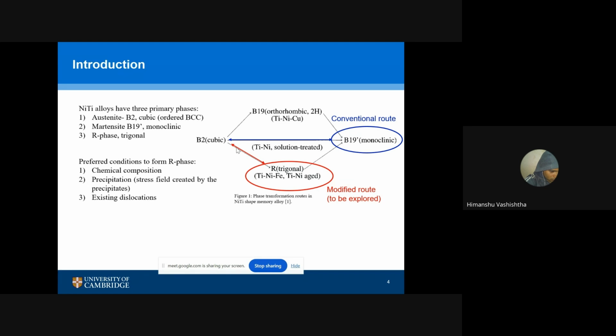So the first one is chemical composition. We can alter the chemical composition that will stabilize the R phase. We can introduce precipitates. What these precipitates are doing is creating local stress fields, and that local stress field is helping the formation of R phase. We will see through experiments in the later slide how it's helping the formation of R phase.